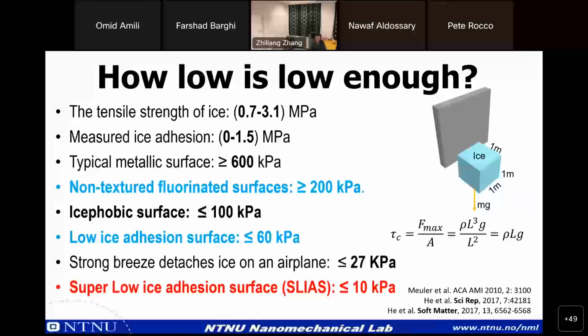There is a definition in the literature. If the ice adhesion strength is below 100 kilopascal, then this surface is called an icephobic surface. And we have a definition: if the ice adhesion strength is below 60 kilopascal, we call this a low ice adhesion surface. We have some reasons; I will show you in the next slide.